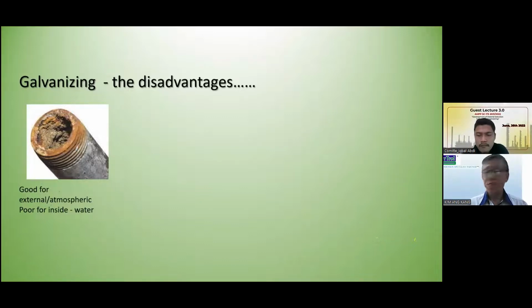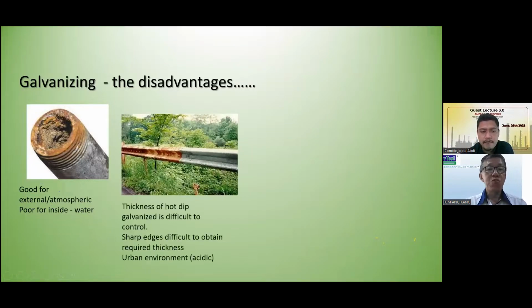Whenever we remove the tap water pipe, what we encounter is that the external of the pipe, where the galvanizing layer could still be intact and in very good condition. However, the internal, which was galvanized at the same time, has thick rust developed inside the pipe. So again, this is an example of good corrosion resistance for the external, where it is exposed to the common atmospheric environment, but very, very poor for the inside of this galvanized pipe because it is in permanent contact with water.